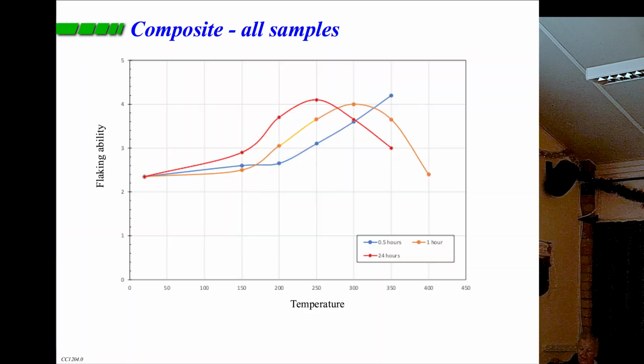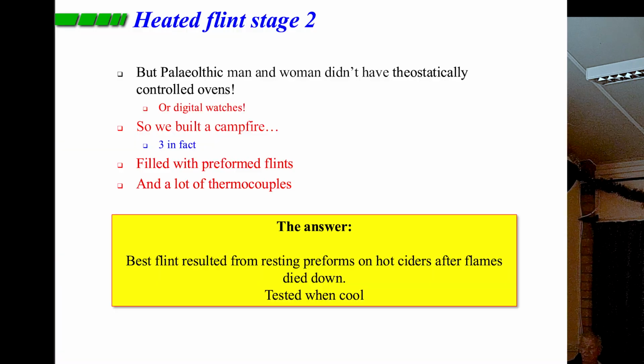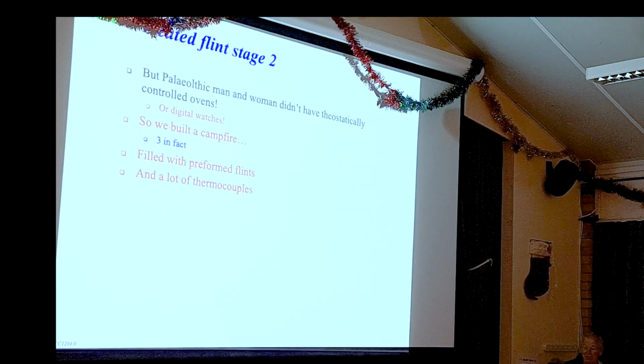And if we combine all the results, you can actually see similar trends. If you're using a high temperature, the quality improves at a fairly low temperature and then decreases if you overheat it. Middle temperature, similar. If we only heat it for a short time, quality keeps getting better and better, and eventually this would also curve off at a higher temperature. So we know that time and temperature are important in how the flint is actually recrystallizing and releasing water, and how that affects the workability.